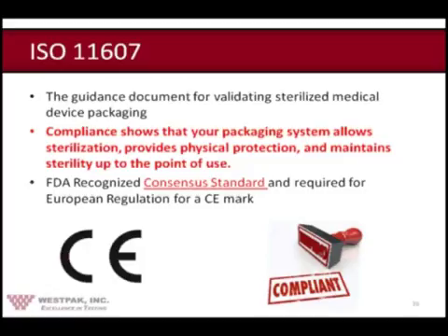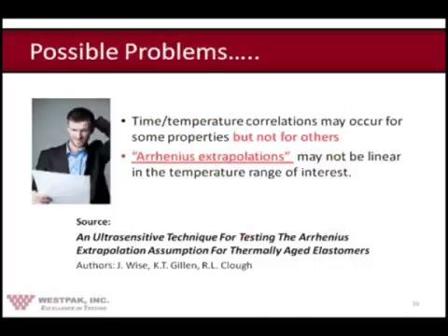In particular, however, there are those who think that it may work for some materials and not others. So it's not what I refer to as a universally accepted ism. It should also be noted that the Arrhenius equation extrapolated beyond very high temperatures, which is really where it started, may result in a non-linear condition not anticipated by regulatory bodies. The reason we mention this is that not everyone agrees that Arrhenius extrapolations, as they're called, result in a true accelerated aging condition.